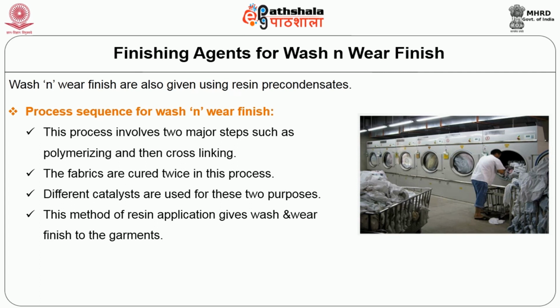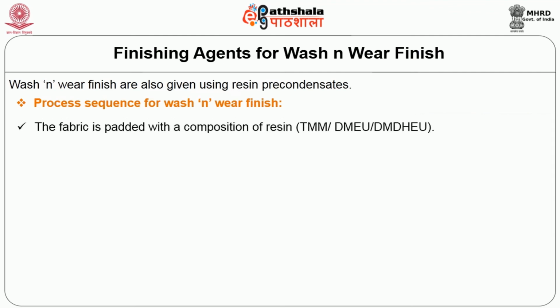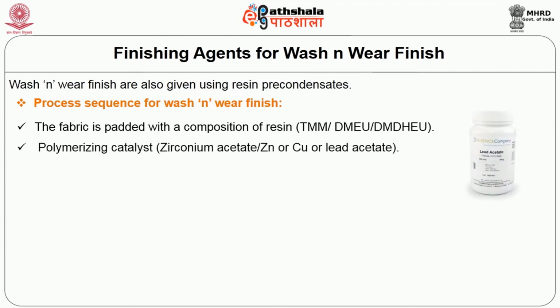The process sequence of wash and wear finish. This process involves two major steps such as polymerizing and then cross-linking. The fabrics are cured twice in this process. Different catalysts are used for these two purposes. This method of resin application gives wash and wear finish to the garments. The fabric is padded with a composition of resin, polymerizing catalysts like zirconium acetate or lead acetate, and wetting agent.